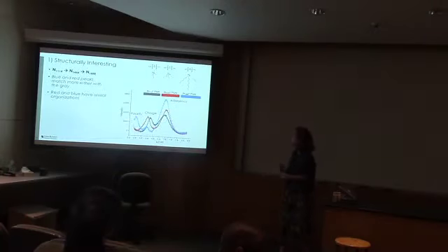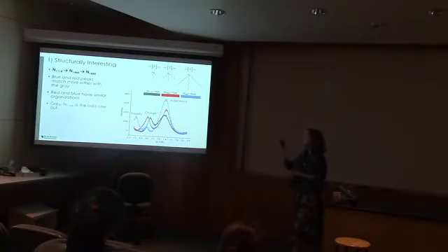So now when we throw N1888 into the picture, we have this blue plot, and a new peak, the polarity peak, is introduced, which I will touch on at the end. But when we look at this plot, we can see that the blue and red peaks match much better together than does the gray. The gray, this N1114, is the odd ionic liquid out in this situation. So we can conclude from the plot that the red and blue, or these two ionic liquids, have similar organizations. And this makes sense when we think about the alkyl tail symmetries being the same. So again, the gray is the odd one out.